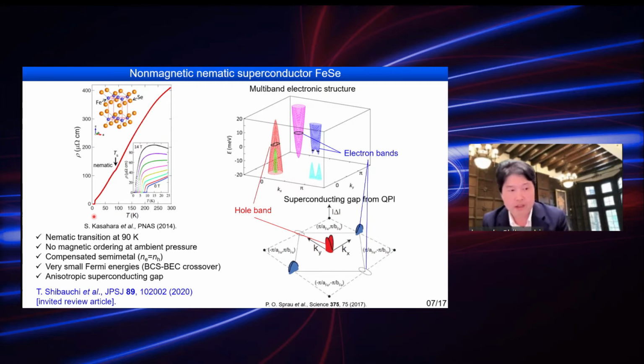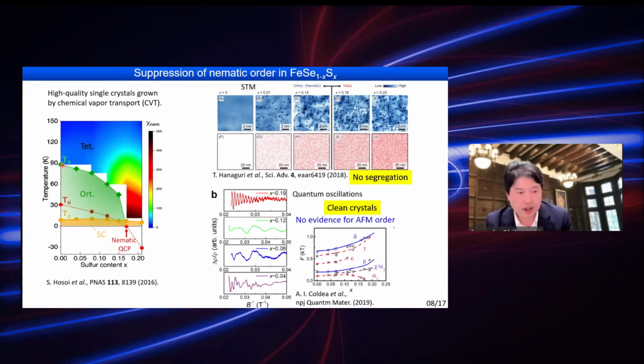This nematic transition can be suppressed by sulfur substitution in the selenium site. You can completely suppress the nematic transition by adding 17% of sulfur.